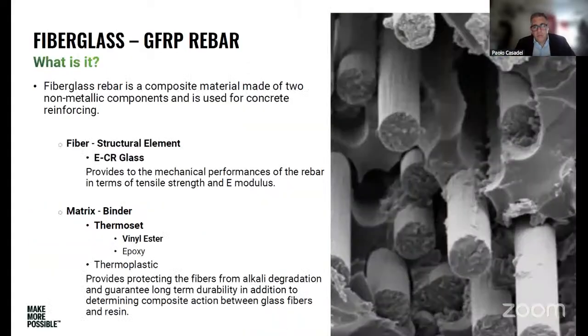Basically, just like all composite materials, which you know very well, for example mud and straw, a traditional construction method. Here we have a matrix made of a resin, and then structural reinforcement made of ECR glass. ECR stands for E corrosion resistant glass, because we added to the chemistry of the glass substances to make it less attackable in an alkali environment. The matrix is a thermoset polymer, usually made of either vinyl ester or epoxy resin.